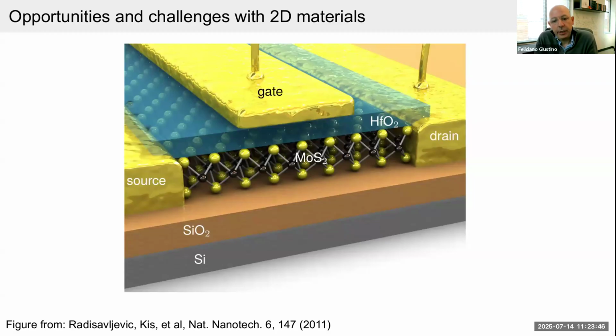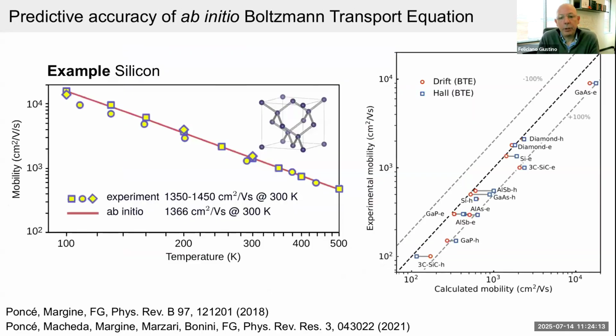So this is the concept, and 2D materials have been around since 2004, and 20 years later, nobody has yet found a 2D material that can rival silicon in terms of carrier mobility in real channels. So despite the promise of 2D materials, there is still a problem in identifying actual materials that will work in real transistors. In this area, what we've been doing is collaborating with experimentalists and companies in order to come up with proposals for potential 2D materials that might fit the bill and deliver the sought-after high electron mobilities. So in this slide, what I'm showing you is just a couple of benchmark calculations.